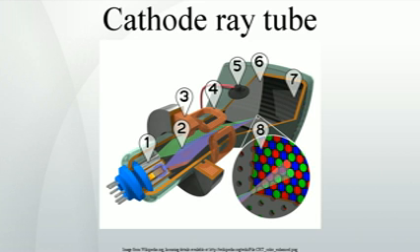In unusual cases of strong magnetization where the internal degaussing field is not sufficient, the shadow mask may be degaussed externally with a stronger portable degausser or demagnetizer. However, an excessively strong magnetic field, whether alternating or constant, may mechanically deform (bend) the shadow mask, causing a permanent color distortion on the display which looks very similar to a magnetization effect.